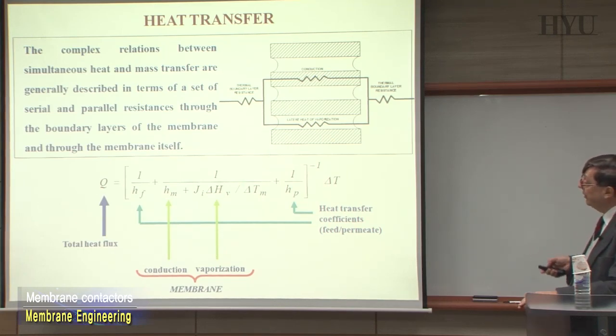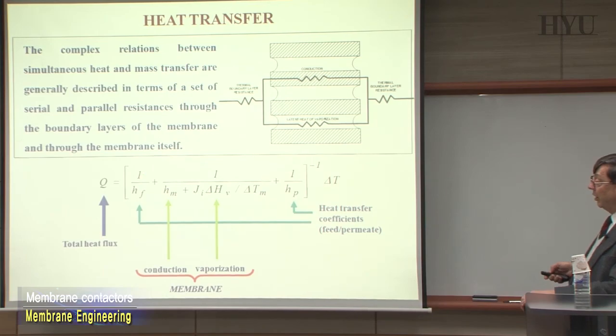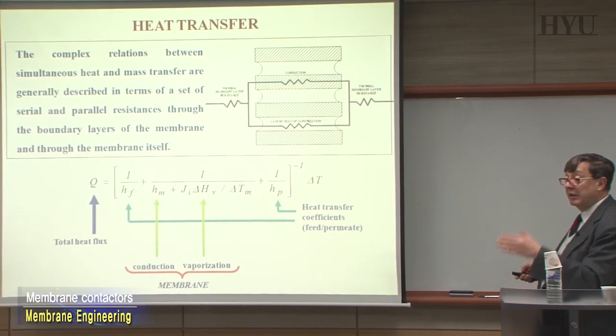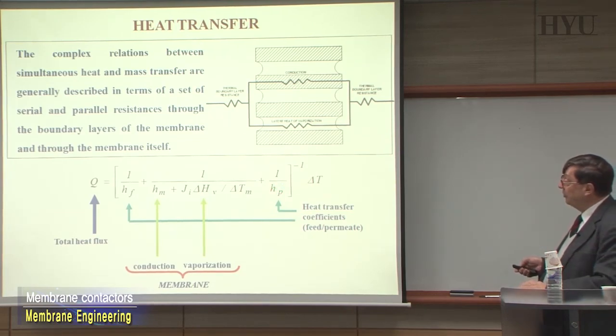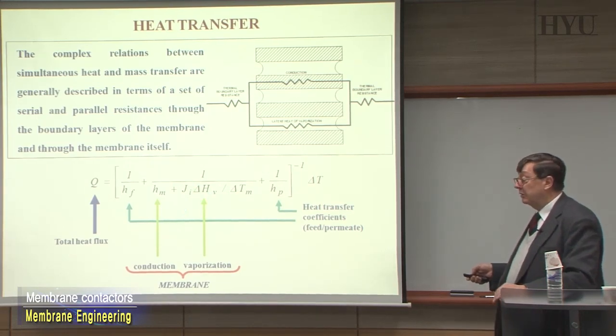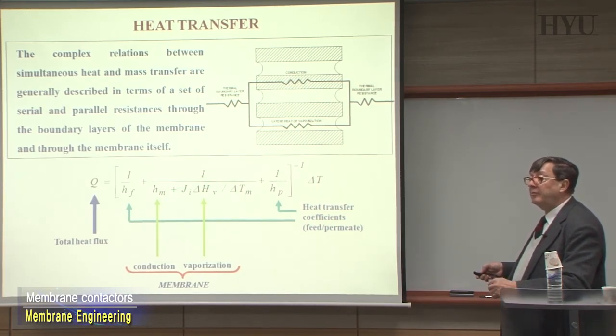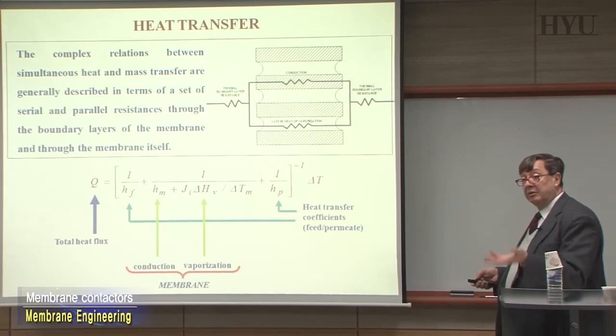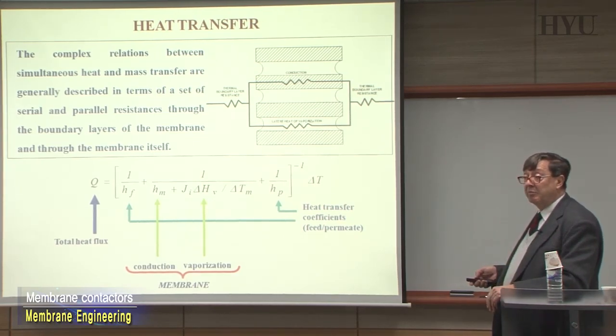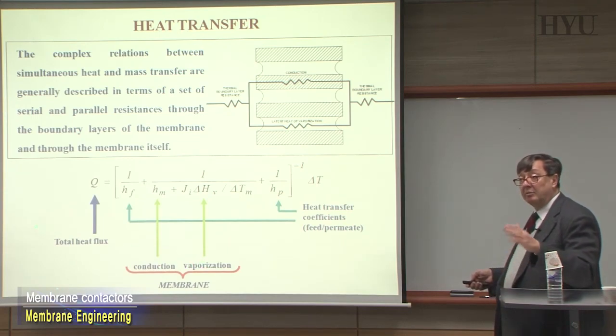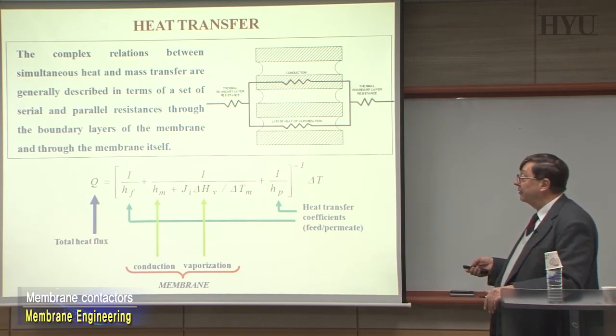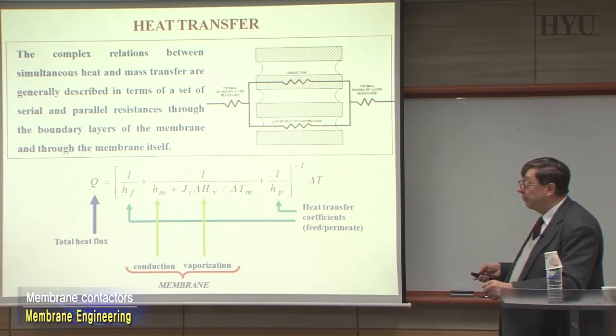Heat transfer is the same story, and here you have that the overall total heat flux across your membrane is related to the heat transfer coefficient of the boundary layer upstream, the heat transfer coefficient of the boundary layer downstream of your membrane, and what is happening in the membrane phase. Now in the membrane phase, as we already discussed before, we can have different kinds of heat transfer. We can have the one by vaporization and the one by conduction. That means part of the heat that you are supplying to the feed side of your membrane is just utilized to vaporize your molecules and put them in vapor phase, through the delta H of the evaporation step. But part of the heat can be just utilized to warm up the membrane, the polymer. And that's not what we are really looking for. That is a problem for us.